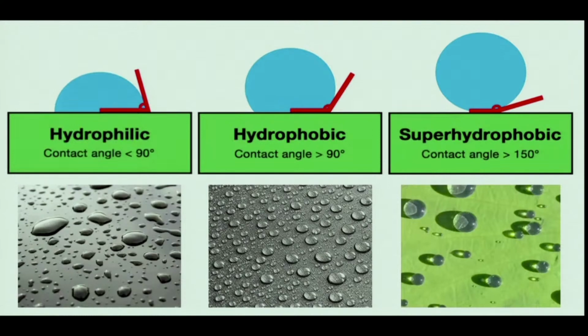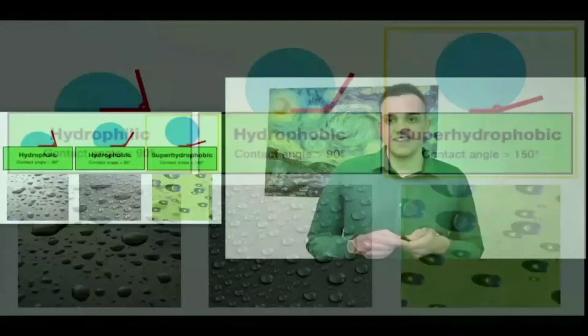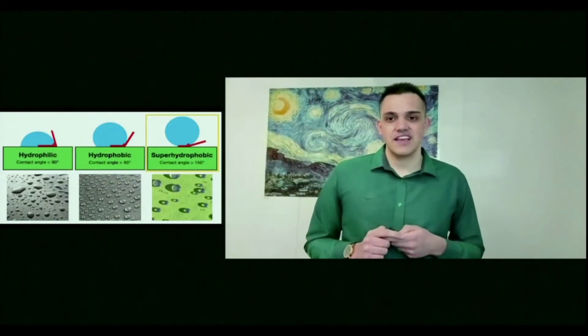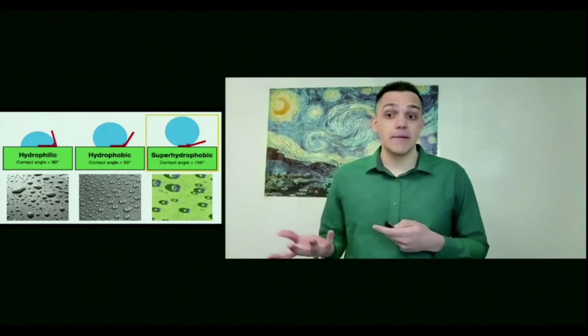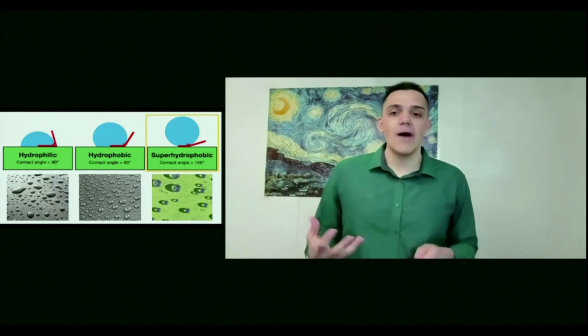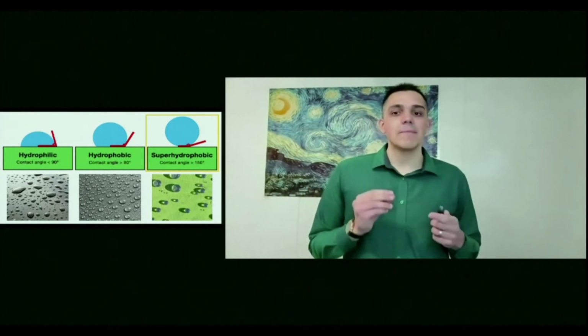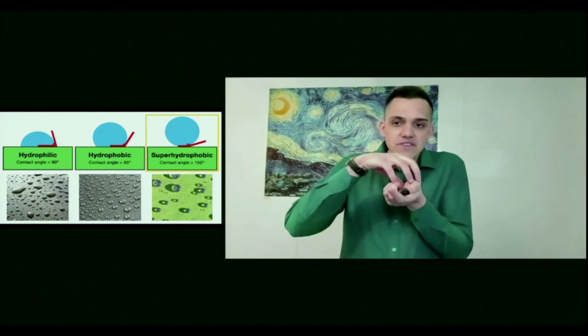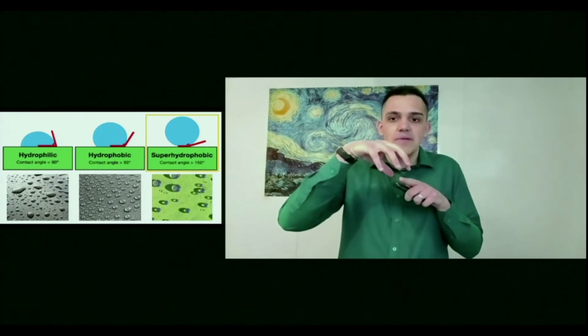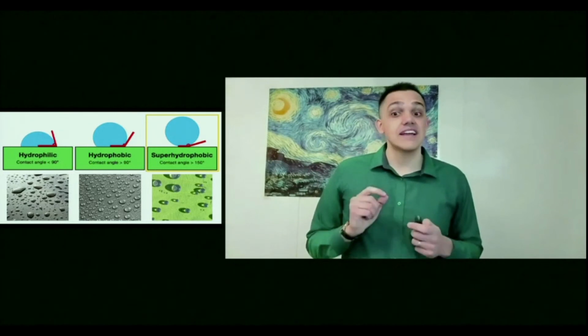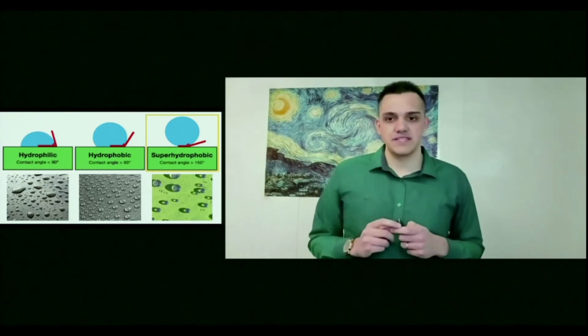And at last, we have a super hydrophobic surface, in which the water droplets are mostly rounded, and they can easily roll off the surface, which is the case of a lotus leaf. And this is what I want to do with the food plastic containers. And we can measure how strongly a material repels water or how hydrophobic it is by placing a droplet of water on the surface and measuring the angle between the droplet and the surface. And that is called a contact angle measurement.